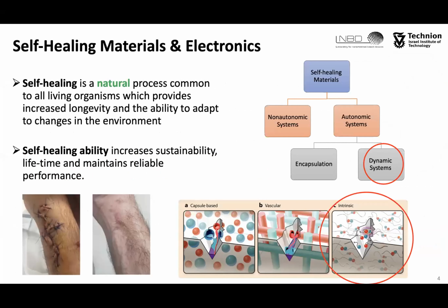In our previous work, we employed autonomic self-healing components to create the first entirely self-healing multifunctional field effect transistor. The devices were based on carbon nanotubes, single-wall carbon nanotubes, and self-healing polymer—in this case, polyurea urethane, PEU. This PEU was adopted as a substrate and as a dielectric layer, using reversible hydrogen and disulfide bonds to achieve